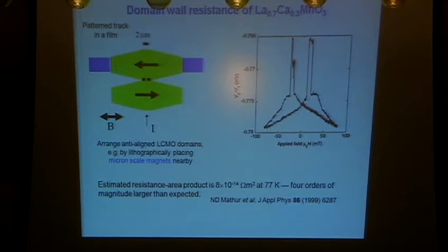about the fact here is the standard resistive switching curve got by taking a junction here where I have two domains of magnetization of the plane, this way and that way, which I can flip, and I measure the resistivity along here, and you get a very large resistivity chunk associated with this, which is quite a bit bigger than one would expect from simple grounds, and undoubtedly would be the kind of number you might get if you were generating a soft spot here where you really suppress the resistivity just by changing the magnetic order.